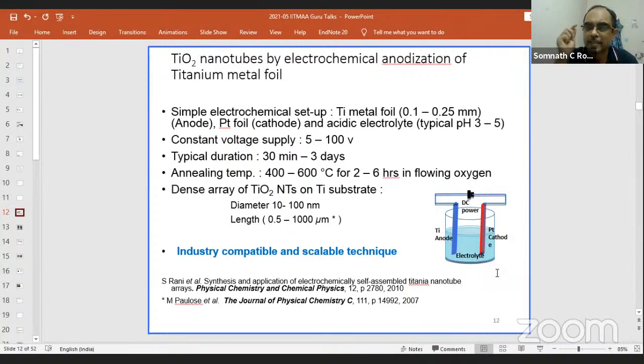We want to make titanium dioxide nanotubes. So what is our source of titanium dioxide? Here we take a titanium metal foil that we use as the anode in our electrochemical process. You have a voltage supply which can give you a voltage of anything. We start from 5 to 100 volts, depending on the length and the diameter you want. We can run this process from 30 minutes to multiple days, up to 3 days, to get very long nanotubes.